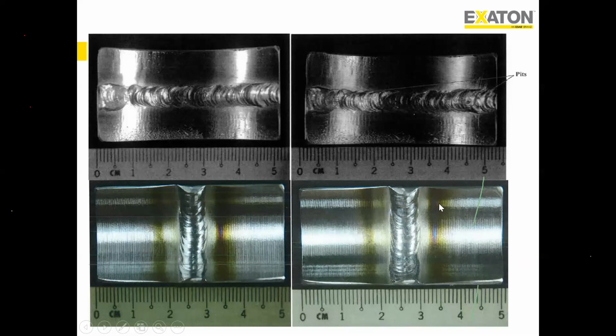Why am I trying to show this one? You can see the heat tints there. Heat tint basically means the amount of oxygen content on the root side is high. Higher oxygen content means lower pitting resistance. So we recommend for the root side the maximum oxygen content should be 50 ppm. 50 and below is always better. From the heat tint itself you can see that if it's much darker, it means your oxygen content was high, or there was high heat input, or it got burned. So an oxygen monitor is very essential for welding of any duplex material.